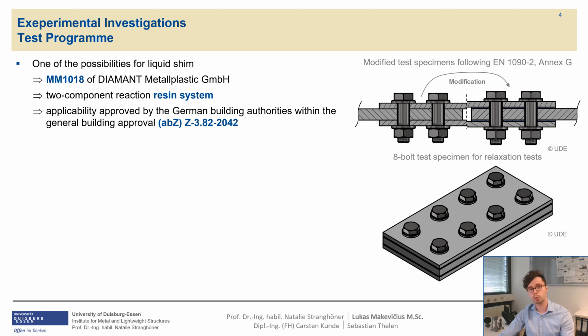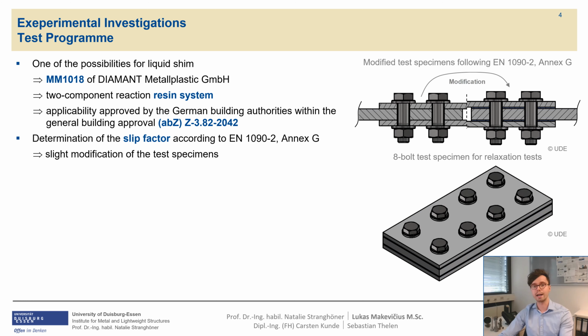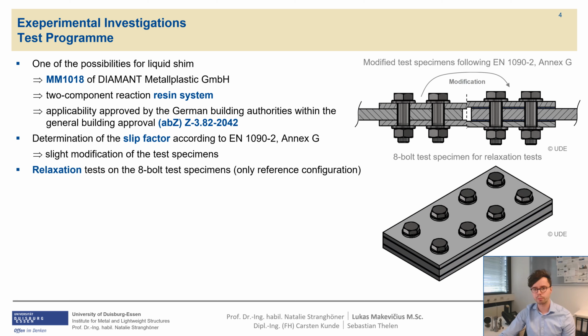In order to answer this question, systematic investigations into preloaded bolted connections with the two-component reaction resin system MM1018 of the company DIAMANT Metallplastic GmbH are currently carried out. The main focus of these investigations lies on the determination of the slip factor according to EN1090 Part 2 Annex G, under consideration of a slight modification of test specimens as can be seen on the right. Furthermore, relaxation tests on 8-bolt test specimens were carried out in order to determine preload losses due to setting effects, creep or relaxation.